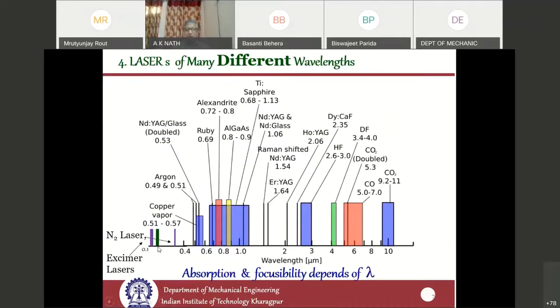Lasers are available in different wavelengths, ranging from ultraviolet lasers like excimer lasers to a large number of varieties up to mid wavelength. The most important lasers used for material processing applications, where you require reasonably high power and pulse energy, are the excimer lasers, the Nd:YAG and glass laser operating at around 1.06 micron, the fiber laser in the same range, the titanium sapphire laser operating in femtosecond pulses, and the CO2 laser. So CO2 laser, Nd:YAG laser, fiber laser, titanium sapphire laser, and excimer laser are the very important lasers for industrial applications.